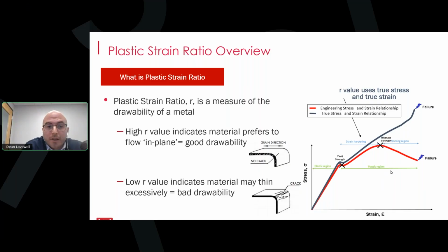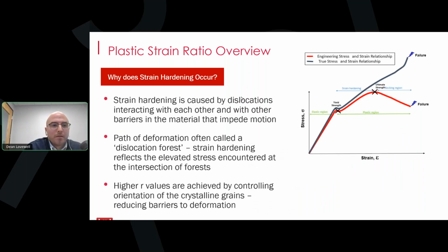So getting back to the calculation, we're measuring how much the specimen's width changes compared to its thickness as it's pulled in tension. This ratio, the width strain divided by the thickness strain, defines the plastic strain ratio. In automotive sheet metal, R value is one of the key parameters that tells us how well a material will perform in deep draw or stretch form applications. Understanding and accurately measuring it helps manufacturers predict formability and update their processes.